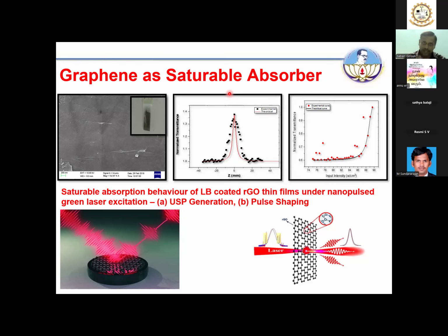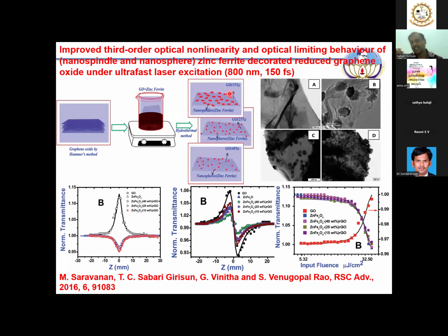So what we did is, we took a saturable absorber and decorated it with different materials, and we tried to induce the process of optical limiting in that material. In our laboratory, we took zinc ferrite and decorated it with reduced graphene oxide, and when we excite it with femtosecond lasers, as you can see in the picture, the graphene, which was a saturable absorber giving a peak pattern, suddenly changes into a valley pattern when zinc ferrite was decorated upon it. Because zinc ferrite is basically a weak reverse saturable absorbing material, when you decorate with zinc ferrite, the material switches its character from saturable absorption to reverse saturable absorption. As a result, it demonstrated optical limiting behavior.